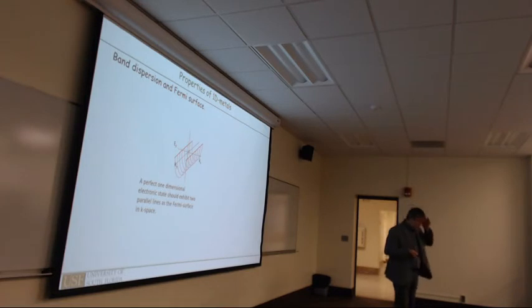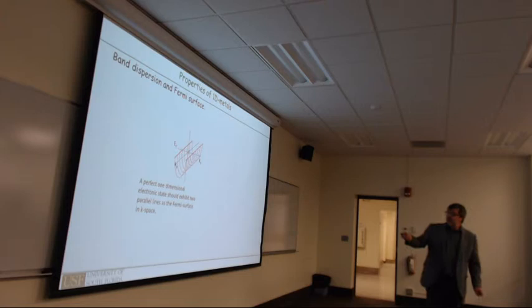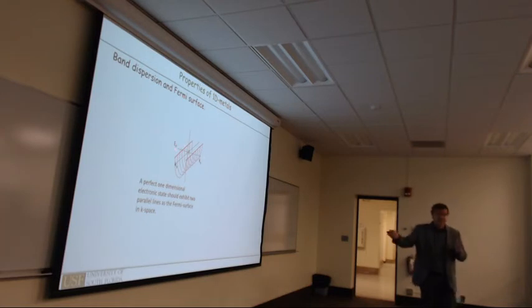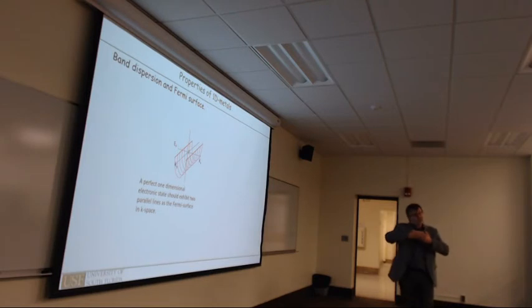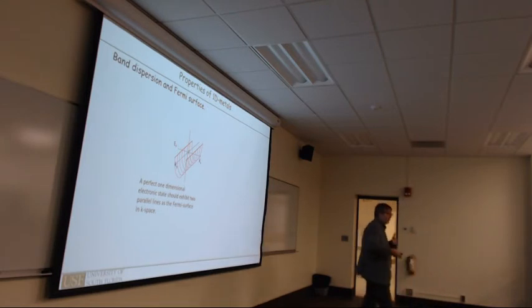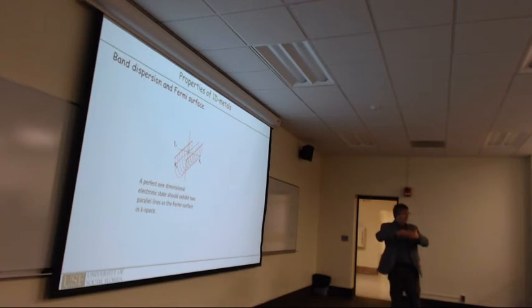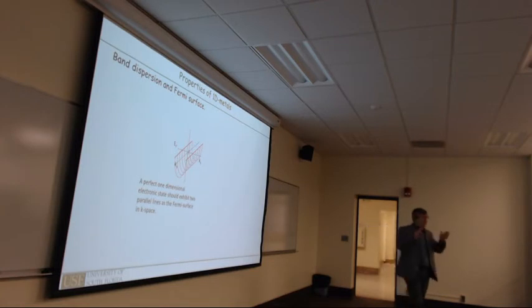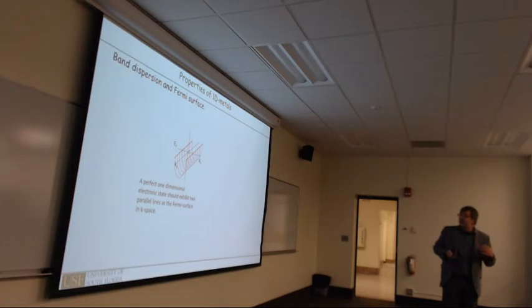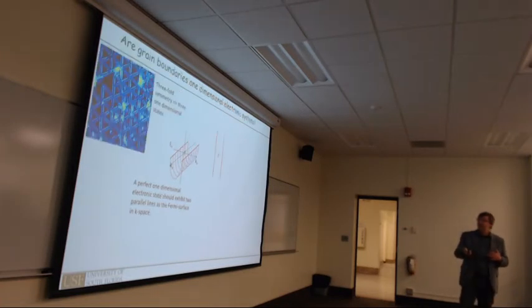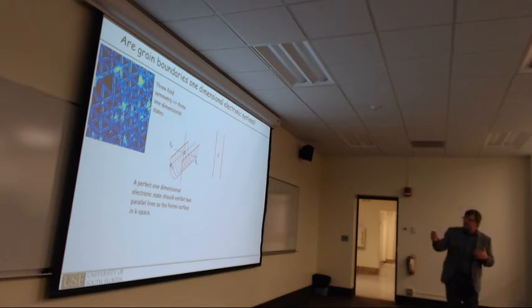If it's really one-dimensional, what we should see is the dispersion along the grain boundary in the kx direction, which would be a parabola, but then perpendicular to the grain boundaries, there's no periodicity, which means in reciprocal space essentially that you have infinitesimally small separation, which gives you essentially a lot of grain boundaries, and your Fermi surface just becomes two parallel sheets of the grain boundary. So your Fermi surface should be two parallel lines. Now in STM we see we have three equivalent directions, so every direction should contribute a Fermi surface of two parallel lines.